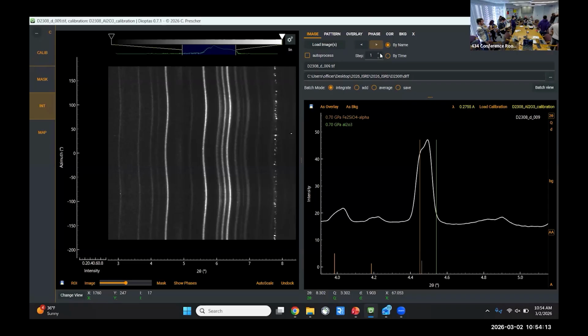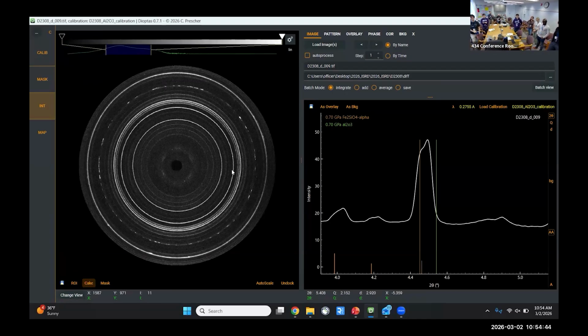And what we do is we fit this ellipse and that will tell us what the differential stress is. So we know our pressure from how close they all are together. And then when we start to stress it, we know our differential stress from the fraction. And you can see this one is starting to build up some stress. So if we go back to the picture, if I pick, say, this line, see if I can see.